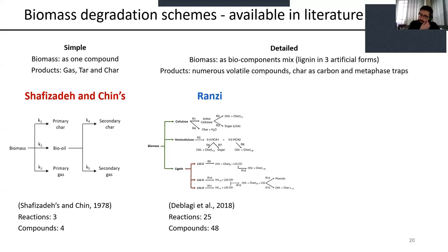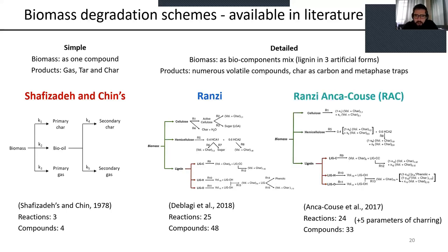To describe the fast pyrolysis, in case the compound retention inside of the biochar structure is longer than fast pyrolysis takes into account, the model does not predict the char yields accurately because of the secondary charring reactions and secondary tar cracking reactions, which produce the soot.